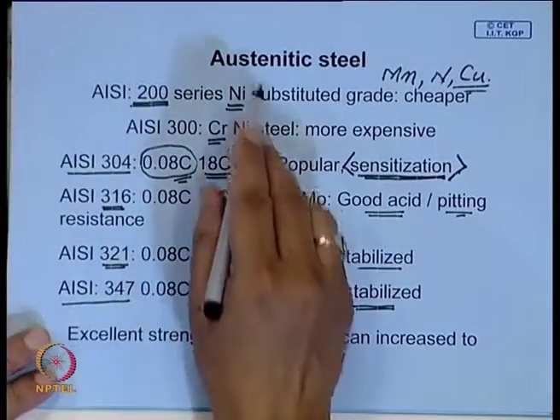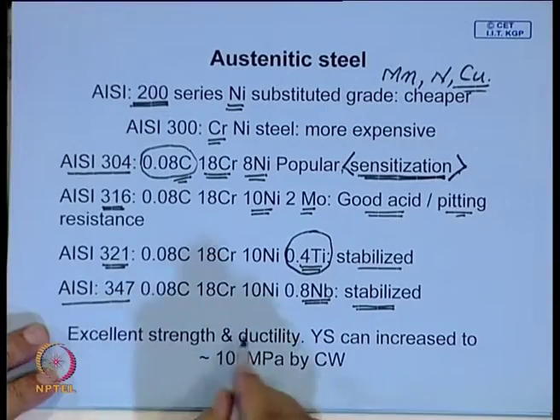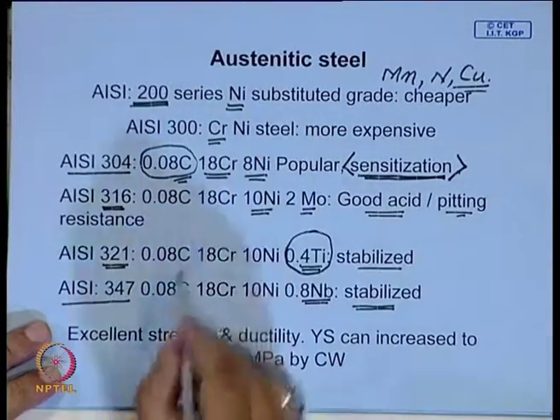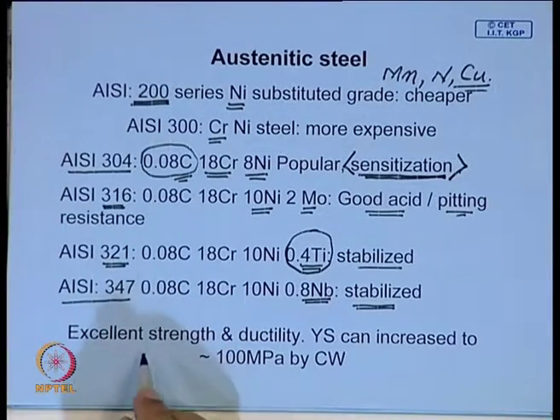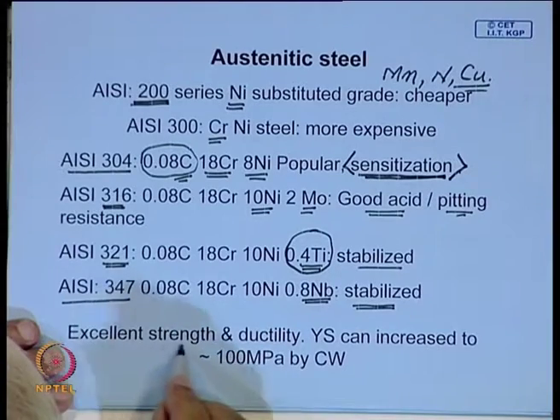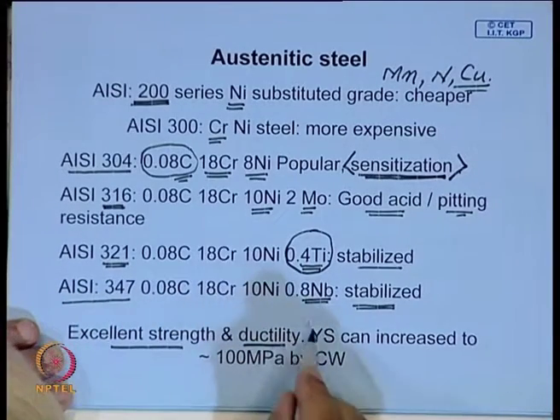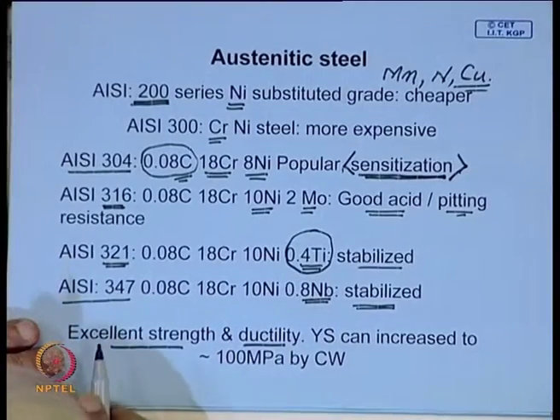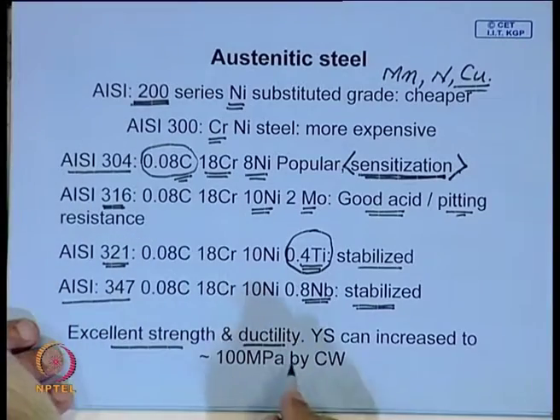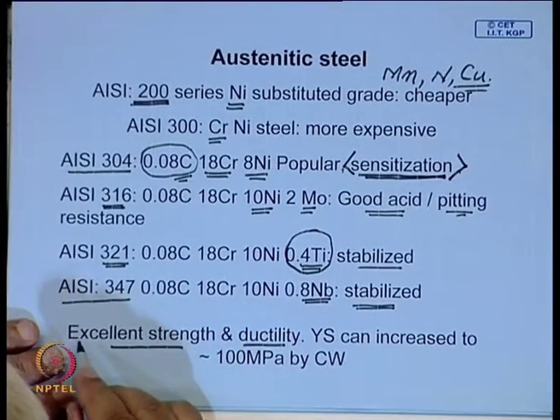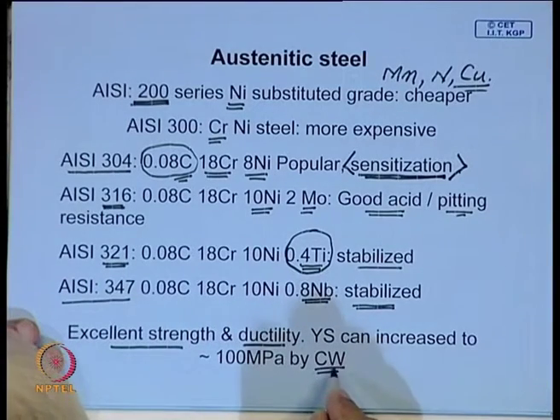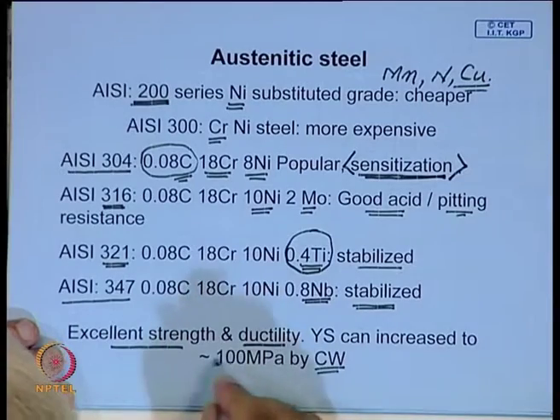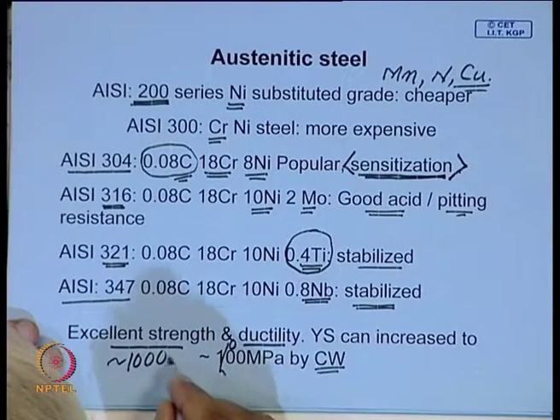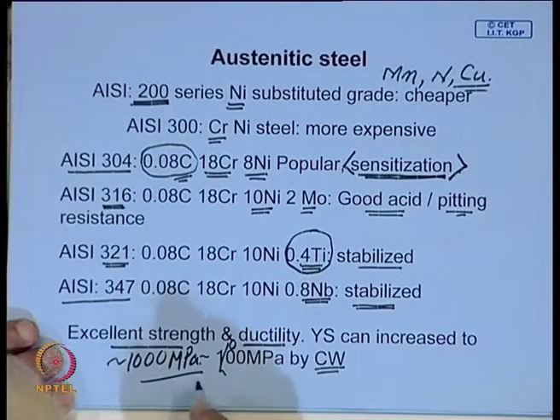Now, the main important property of austenitic stainless steel is that it has excellent corrosion and oxidation resistance. It can be used for high temperature applications, and it has not only high strength but good ductility as well. But the main problem is that it is not amenable to any heat treatment; martensitic heat treatment is not possible. The only way it can be strengthened is by cold work, and yield strength can be increased up to around 1000 MPa by cold work. By giving cold work, you can increase its strength significantly.